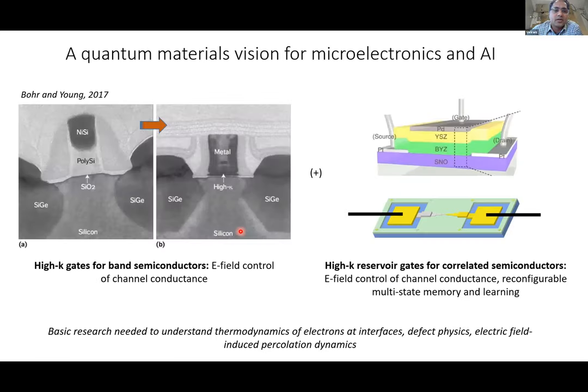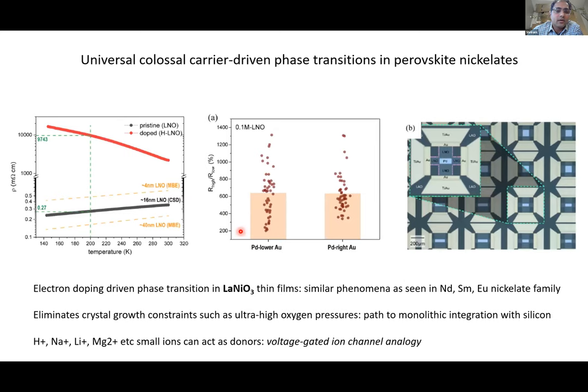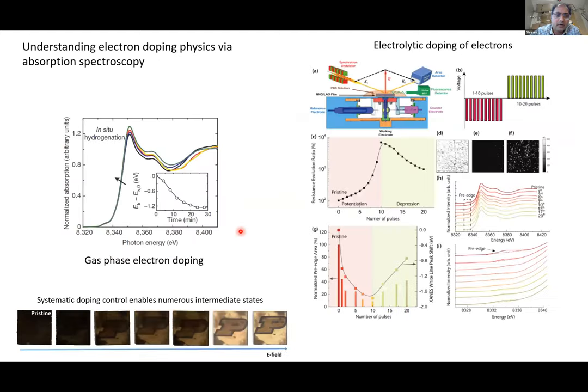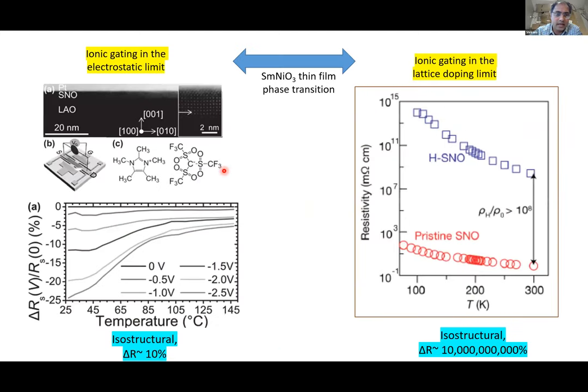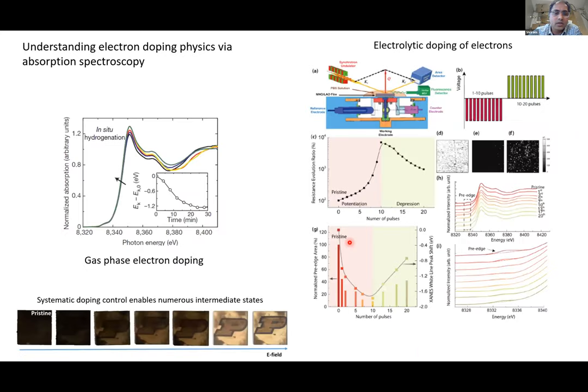Yes, it's a great question. We looked at hydrogen initially because we had some very simple techniques to introduce the dopant using electrodes from the gas phase. That was how we got started, because we were working on these ionic liquid gates for hafnium oxide and all these different gates for many years, and then we wanted to increase the charge carrier density. But then we wanted to understand whether hydrogen was the reason for the phase transition or it's the electron. At that time, we didn't know this.